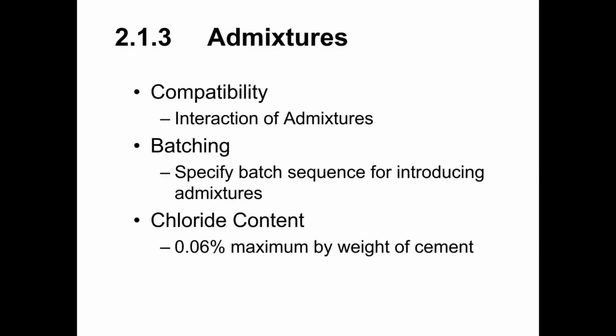Next, revisiting admixtures. Just a few things to keep in mind when using admixtures in our concrete. One is compatibility. Admixtures don't always interact with each other well. If all of your admixtures come from the same admixture supplier, that supplier is well aware of how their different admixtures interact with each other, and they can give you guidance on which admixtures should be used with each other and which should not be used with each other.